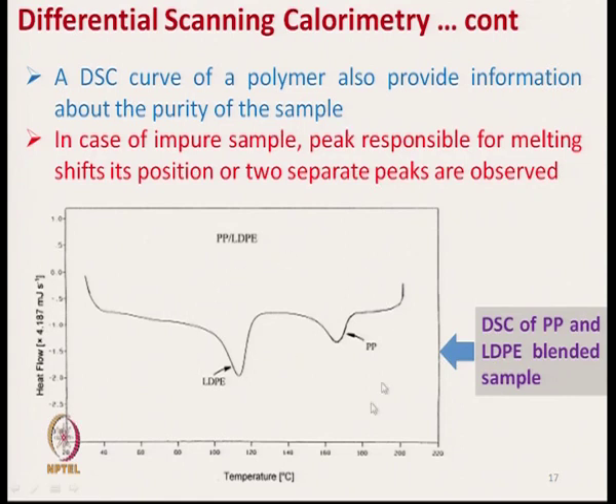So this curve is of a blend of polypropylene and low density polyethylene, a blended sample. As this is blended, polypropylene will have a certain melting point here, and LDPE will have another melting point here. So these two different peaks show that this polymer is actually a mixture of polypropylene and LDPE.